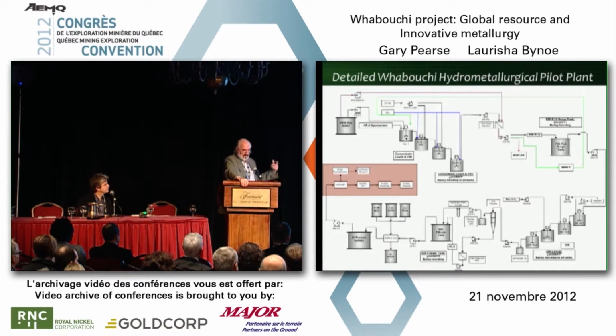We use some of our product to raise the pH of the solution for a secondary purification, and then that goes back into the stream and is recovered again. We reduce everything down. We get rid of the iron, aluminum, silicon, and manganese, and so on. And the last two things are calcium and magnesium, which we have to move down to below 5 parts per million in the solution to be able to make the products themselves. And we found we can remove it right down to 1 part per million, depending on how much of the ion exchange process we want to employ to do that.